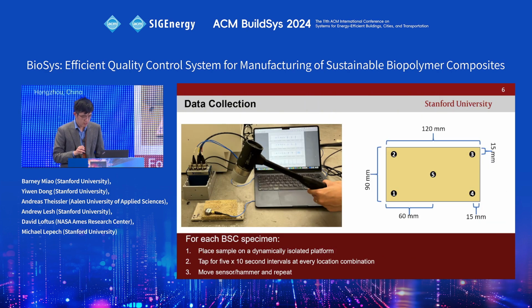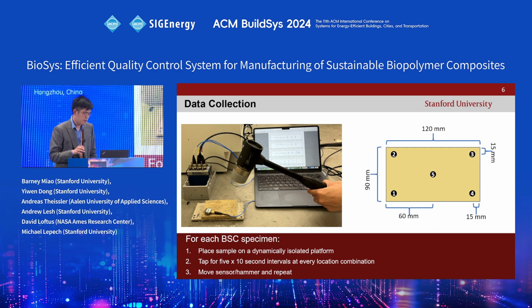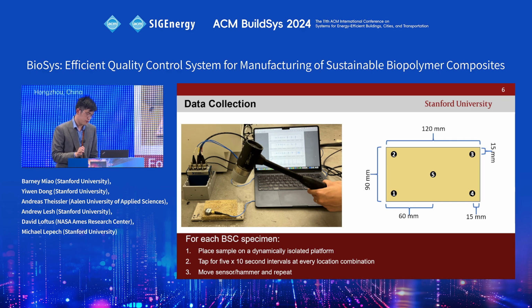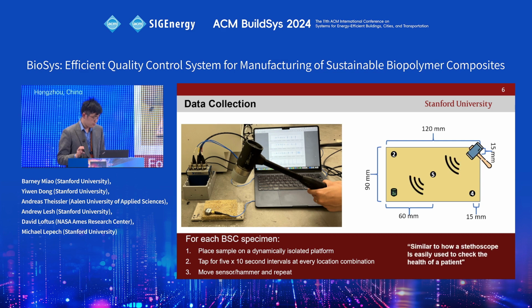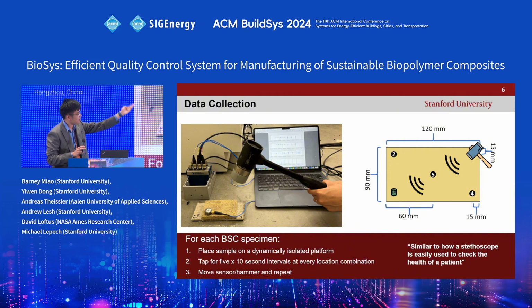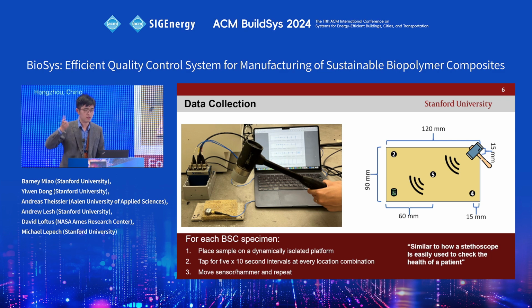So for our data collection, you can see here the BSC sample is mounted on a dynamically isolated platform, so it's separated from the ground. In this case, for each sample, you would imagine you put your sensor in the bottom left corner and you tap on the top right corner, and you basically tap this for 5 continuous 10-second time intervals to collect your data. And you would basically repeat this for every sensor and hammer pairing over the specimen. That's how you would collect the data.